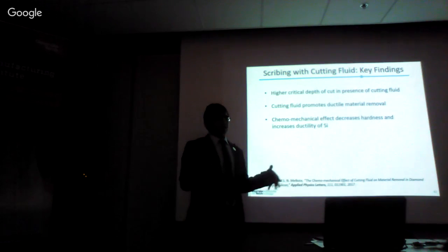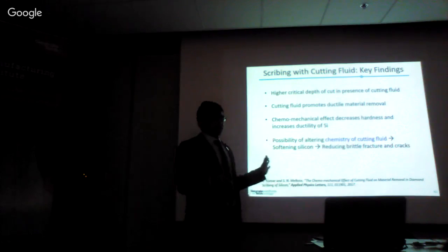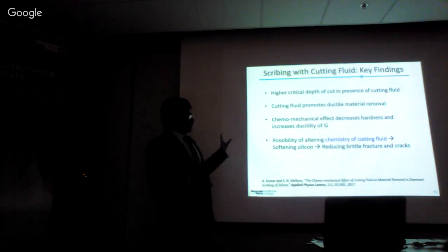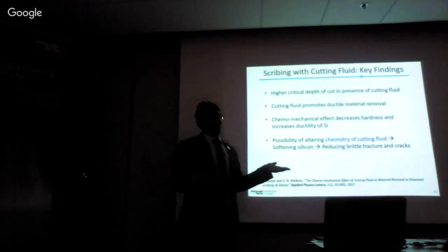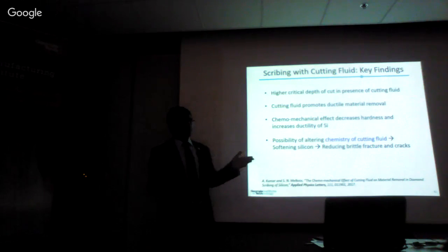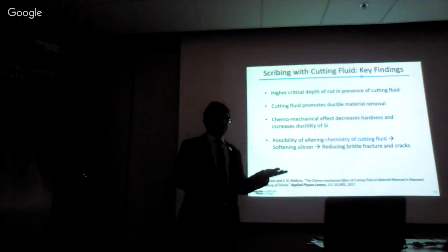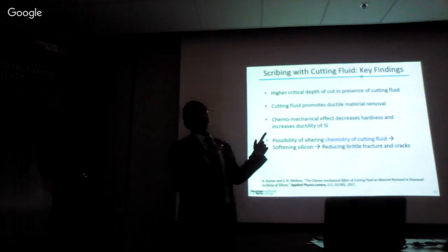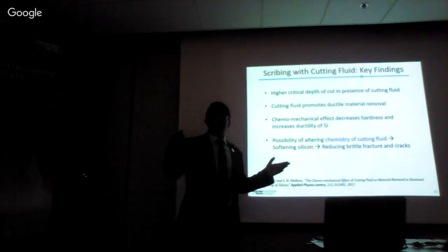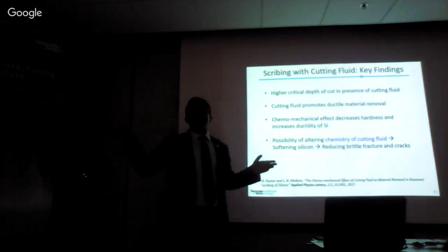And the reason for that is the chemomechanical effect, decreasing the hardness and increasing the ductility of silicon. The key takeaway from here is we can possibly alter the chemistry of cutting fluid in future. We can soften silicon, reducing brittle fracture and promoting ductile mode material removal, and thus could speak to our challenges of reducing the micro cracks in the surface and subsurface of the sawn silicon wafers.